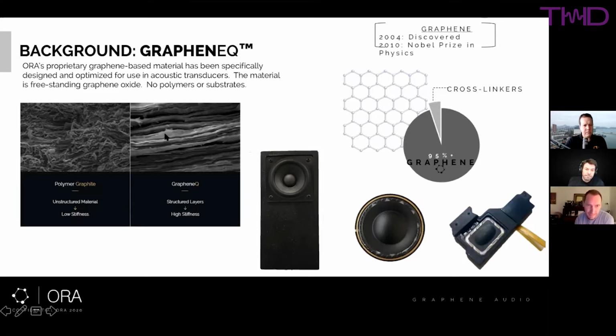So, this is a little bit that's flopped up, but you see it's almost translucent because it's so thin. And these layers of carbon are basically stacked on top of each other in a laminate structure that allows us to take advantage of the characteristics of graphene, right? Our material is not as stiff as a single layer of pristine graphene would be, but we can leverage the very interesting mechanical properties of graphene to create this laminate material that takes advantage of those characteristics.